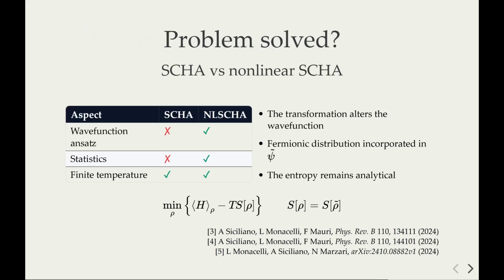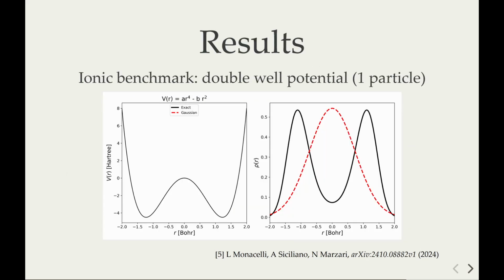The other very nice thing is that one of the key properties of the self-consistent harmonic theory is that we have analytical entropy. This means we can compute free energy directly without any thermodynamic integration. It's very quick, and we don't want to lose this property. But thankfully, if the transformation is invertible, then we can prove that the entropy in the auxiliary space and in the real space is exactly the same. So we preserve all the very good aspects of this theory. Now let me go to some results.